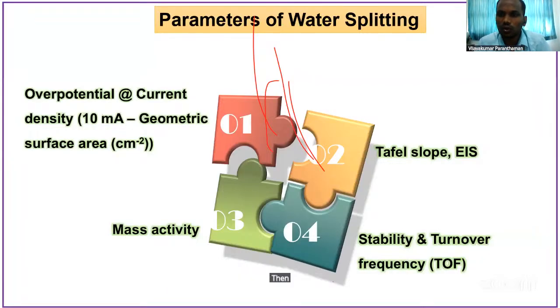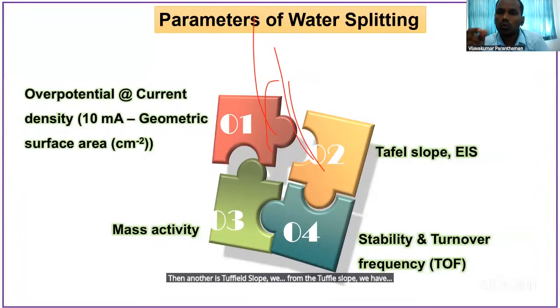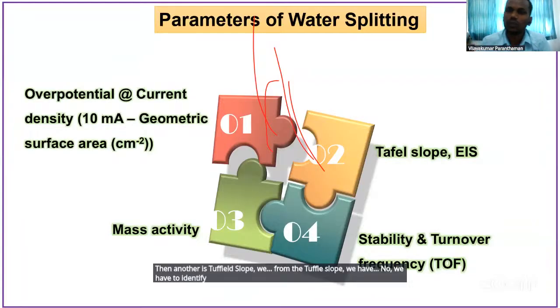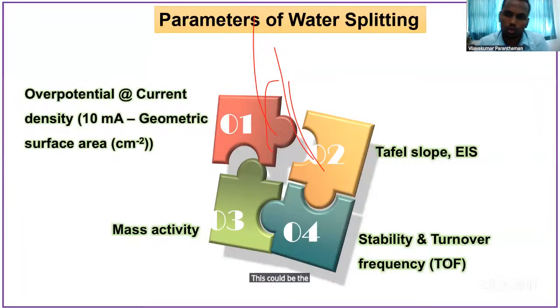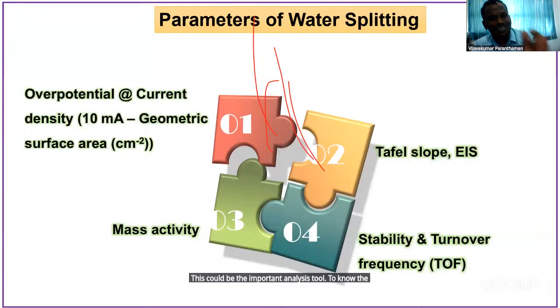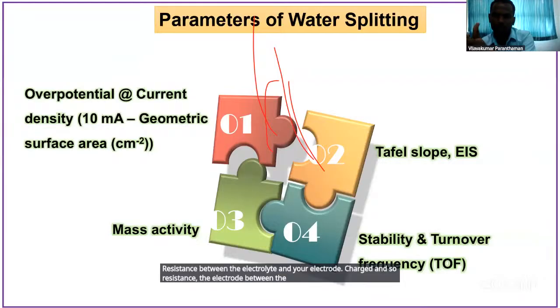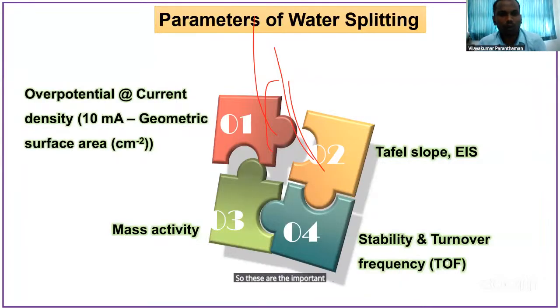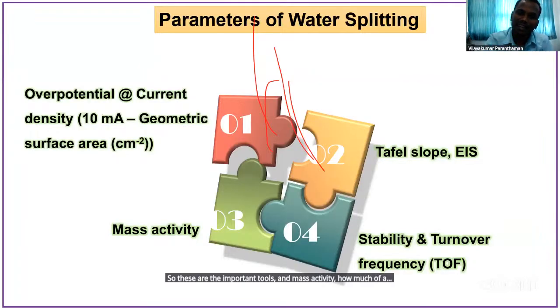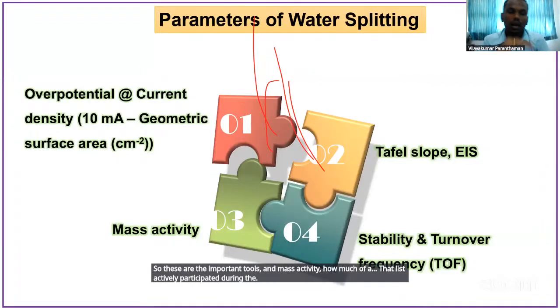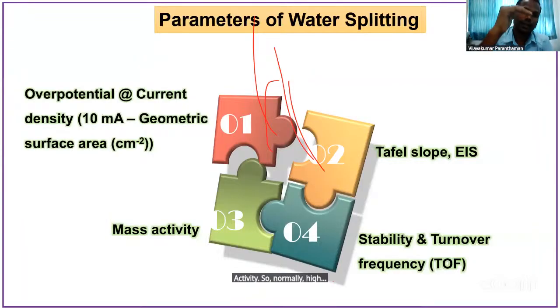Then another is the Tafel slope. From the Tafel slope we identify the reaction kinetics of the material. Then electrochemical impedance spectra could be an important analysis tool to know the series resistance between the electrolyte and your electrode, and the charge transfer resistance between the electrode and your substrate. So these are the important tools. And mass activity: how much of the catalyst actively participated during the activity. Normally a high mass activity gives greater activity of OER or HER.